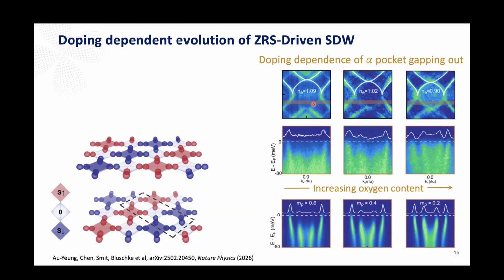Okay, great. So the gap is there and presumably will be there in a much bigger portion of the Fermi surface. But because of the domain, as Christine was saying, when you have two rotated domains, it becomes evident in these non-high symmetry positions, but the gap is there. Presumably there will be temperature dependence, which we have not done in this particular work yet. But this gapping out is similar between 1313 and 2222. Yes, so that would suggest that the density wave vector had better be comparable in the two cases.